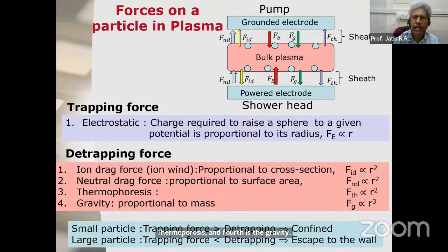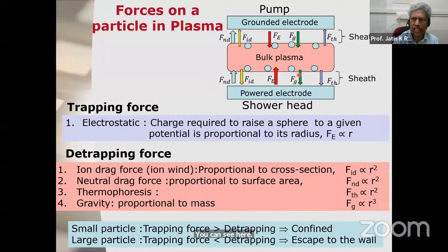So you can see here in this one. Gravity will make things fall down, everything is coming this side, whereas the ion drags will go from both sides, whereas neutral drag will go only one side, and thermophoresis can be from both sides. So this one and this one will allow particles to be deposited here. As you can see here, for small particles, this force is much bigger than this, so they will be trapped.